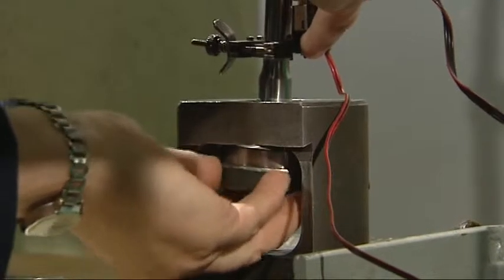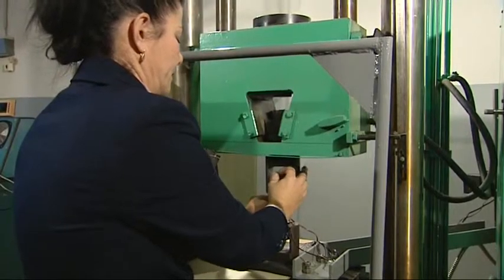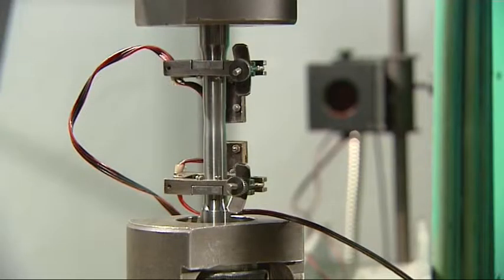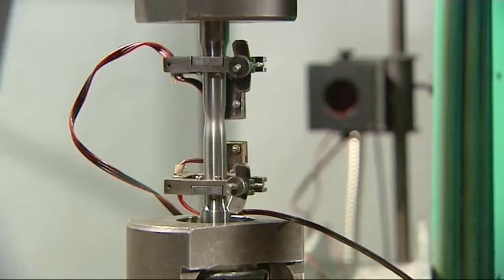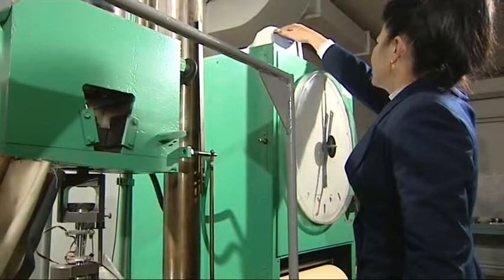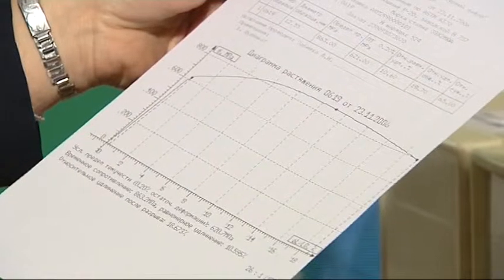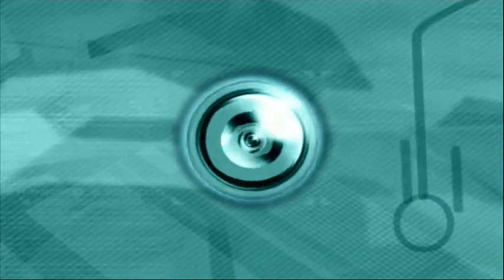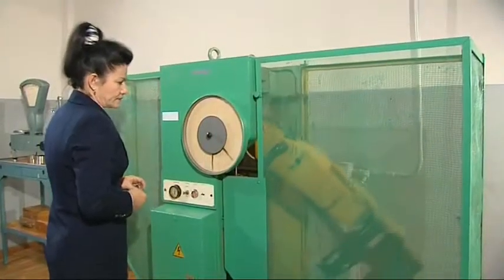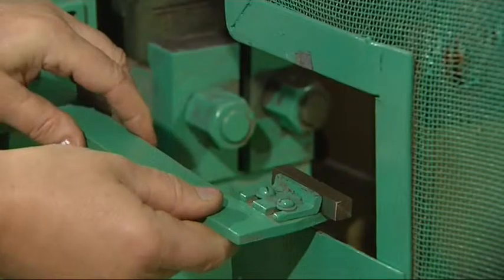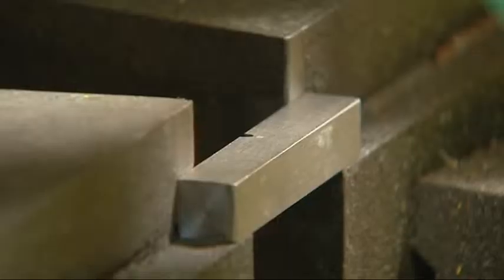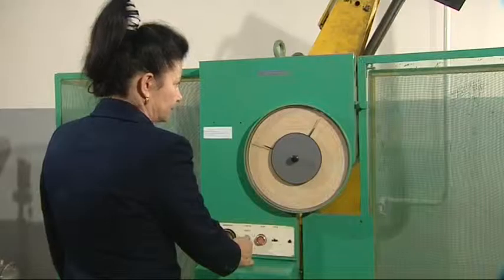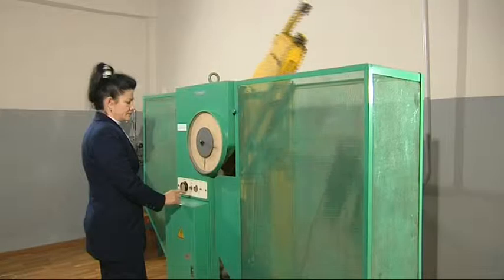Parts are tensile strength tested on a tensile testing machine fully in accordance with ASTM A370 standard with automated data record and processing. V-notch Charpy toughness of specimens is determined according to ASTM A370 and ASTM E23 standards.